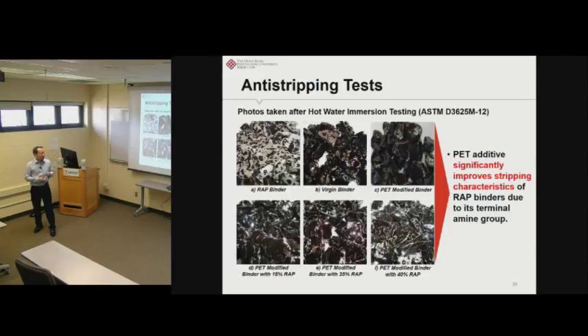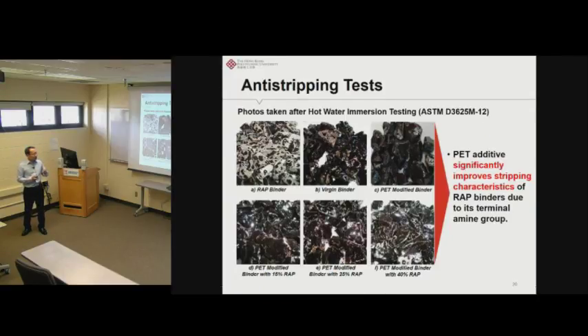And the main reason is due to these amine groups. Such amine groups can serve as a bridge between the asphalt binder and the aggregate. It has good adhesion properties with both asphalt binder and aggregate. Actually, amine material also has been used in the literature as an anti-stripping additive.